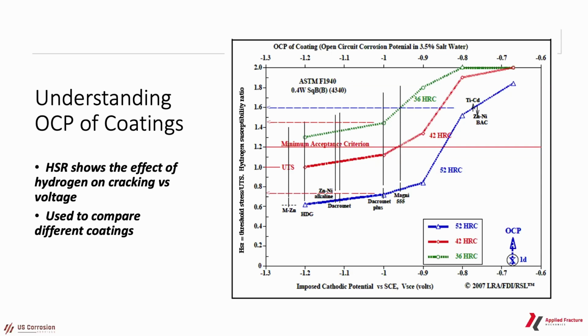And what you can see here is in these high strength materials, there's only a handful of coatings that are actually acceptable. And I would consider all the rest of these to be problematic at this high strength level. As you go to more medium strengths, you see a few more of these that start to be close to or in the acceptable range. And then once you drop down to 36 HRC, we actually see that all of these coatings turned out to be acceptable, or at least above the minimum acceptance criteria.